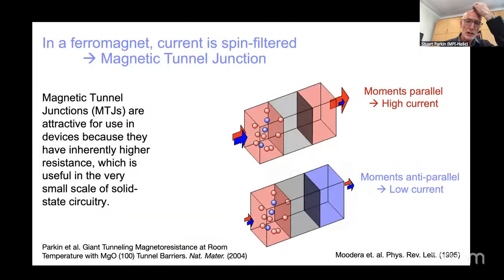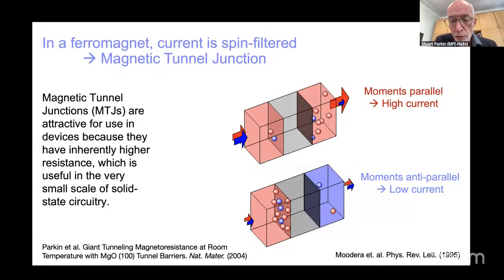I want to talk to you about two possible ideas. One is another proposal we made that we could build a magnetic memory using not a spin valve concept, but a magnetic tunneling device. The structure is the same as a spin valve: two magnetic layers, separated not by a copper layer, but by an even thinner layer formed from an insulator, shown here as gray. This is some work of myself, and also Jagadish Moodera at MIT, who was one of the first to demonstrate at room temperature that you could achieve a change in resistance of tunneling between two magnetic layers, shown here as red, through the gray layer, which is a very, very thin insulating layer. And the tunneling probability depends on the availability of spin polarized states.